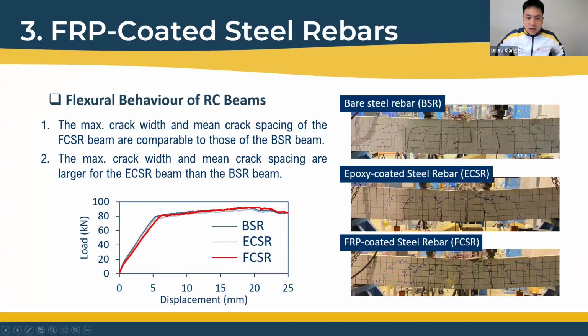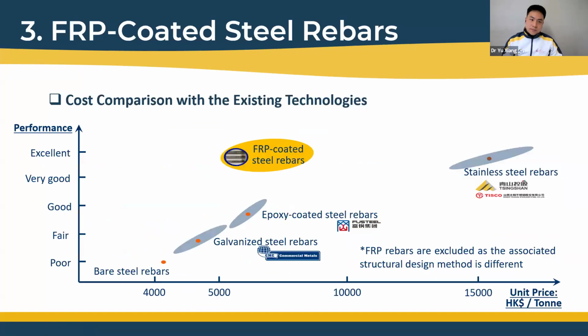This first confirms what was shown in the previous slide, that the bond performance of FRP-coated steel rebar is much better than epoxy-coated steel rebar, and also confirms that the flexural performance of the beam reinforced with FRP-coated steel rebar is better.